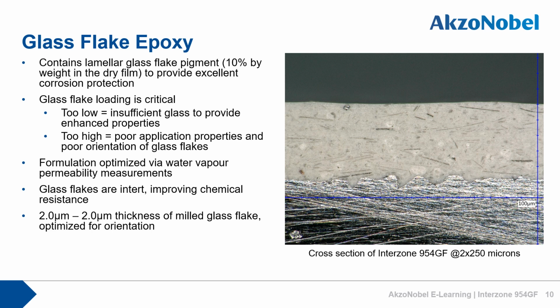The cross section also gives you a glimpse into the proportion of glass flake pigmentation in the product. In the case of 954GF, the glass flake pigmentation is 10% by volume. As the bullet point here says, the proportion of glass flake, what we refer to as loading, is critical. Too low and it is insufficient to provide any enhanced properties at all. We see several products on the market that claim to be glass flake epoxies, which have less than 3% glass flake pigmentation. At those low levels, they really don't make any difference to the performance of the product.